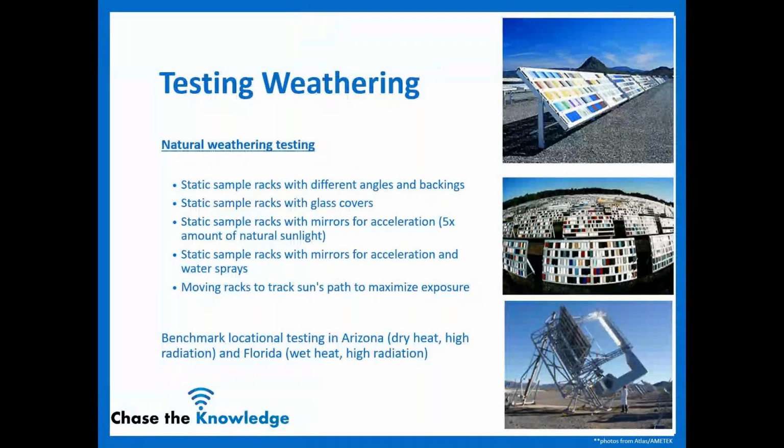Okay, so the other thing to note before we get fully into the testing is for the physical performance and loss of properties, what you're going to find first is your color shift. Right at that surface where it's being attacked, you're going to see the color change or the gloss loss. It has to get a little bit further into the bulk of the material or the product to crack it enough or to embrittle it enough to cause issues with performance. And so typically you'll see color shifts first, and then you'll start losing your property performance. So it's not a bad thing to also do property retention testing before and after exposure to get an idea of how it's performing. And so that's weathering, what it is, what it kind of looks like, what happens.